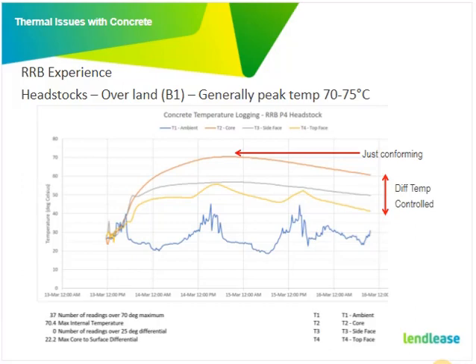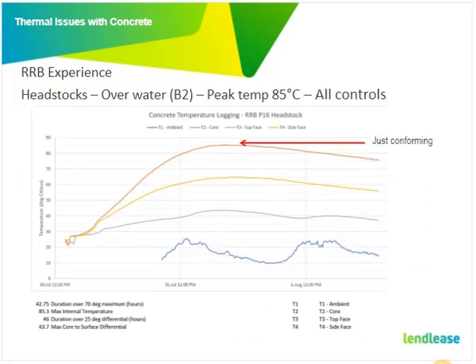The shells are pretty effective. Over the water, even with all those additives applied, it was a B2 mix. We had instances where we ended up with up to 85 degrees. So that was not ideal. But it just shows you apply all these controls, and how on earth we were ever going to achieve 70 degrees, I do not know.